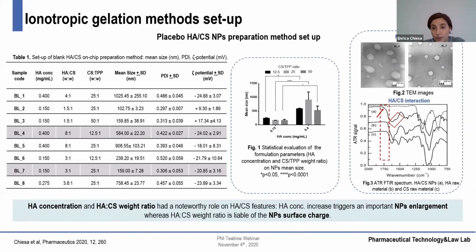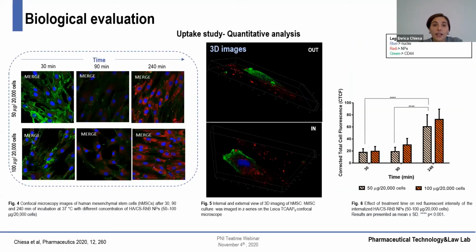Moreover, a new shoulder appears here, and it is reported in the literature to be evidence of the hyaluronic acid protonation occurring during the polyelectrolyte complex formation. The uptake profile of our nanoparticle was tested at 30, 90 minutes, and 4 hours of incubation.